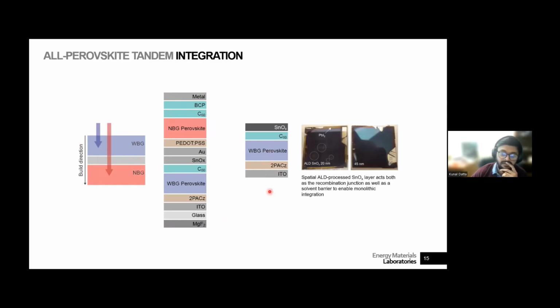And here it serves two purposes. Not just does this have an electrical role, but it also has a role with respect to the solvent barrier. So, for example, if you're depositing this cell on top of this, it should protect it. So we try to simulate that by just taking this stack, just this cell, and spin coating water on it. And you can quite clearly see that depending on the thickness of this ALD oxide layer, you start